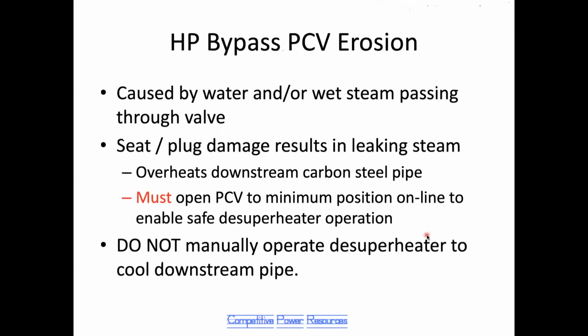There we go. So this erosion is caused by water or wet steam passing through the pressure control valve. And when it does that, it damages the seat and plug and the seating surfaces. Once that valve starts leaking, you're now leaking hot steam into the downstream pipe, which is generally made of carbon steel. So as that leak rate increases, you eventually reach a point where the downstream temperature exceeds around 780 to 800 degrees Fahrenheit, and it will then damage the carbon steel pipe.